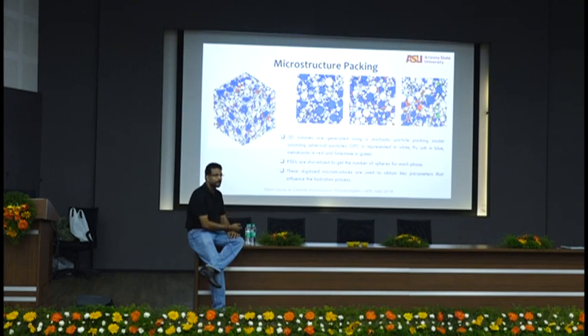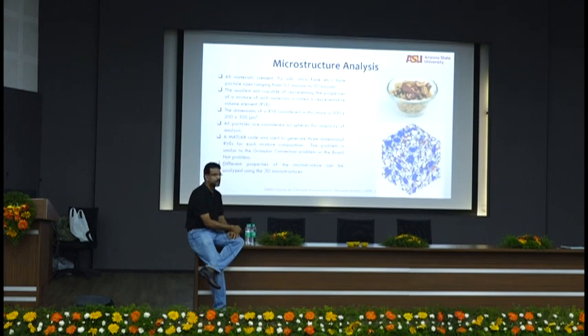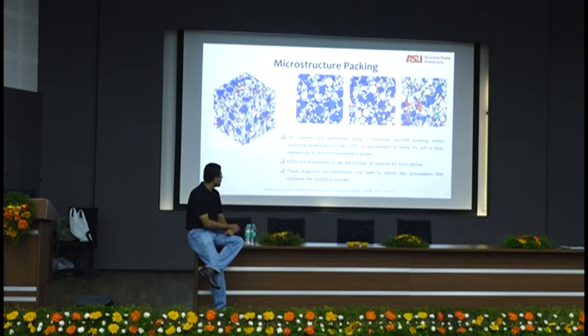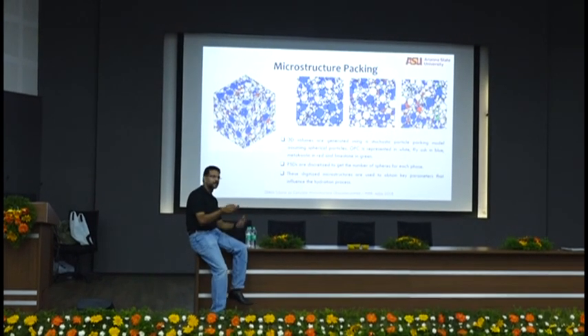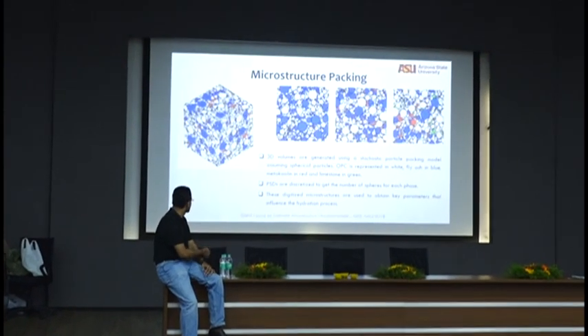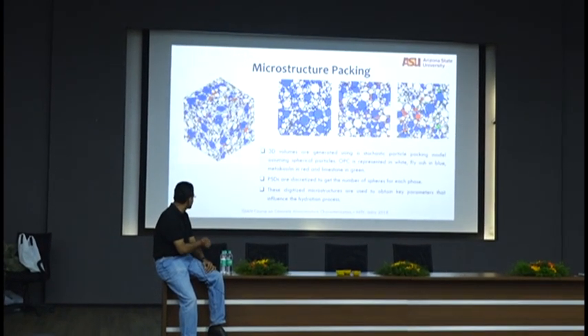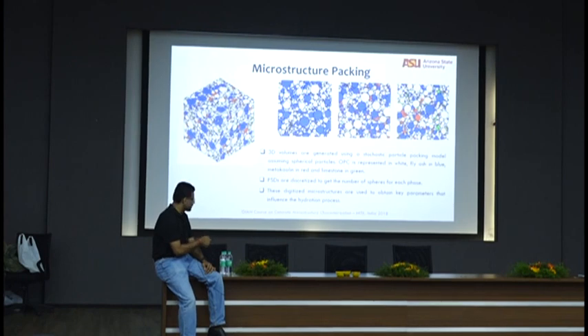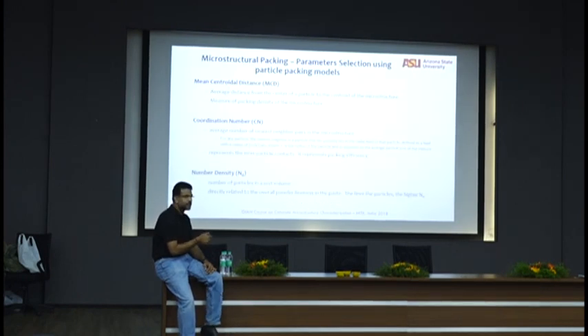So these particles that the computer takes, they are unreacted, right? Yes, this is the fresh state. Packing always happens in the fresh state. That volume might change, but if I get the maximum packing to start with, I'll get the maximum packing to end with, because what you need is the densest possible microstructure. But remember, there is space between these particles based on the water cement ratio you've chosen, so there's place to react too, because you have a certain amount of water. Okay, so you have the 3D volumes that we have generated, a digitized microstructure.